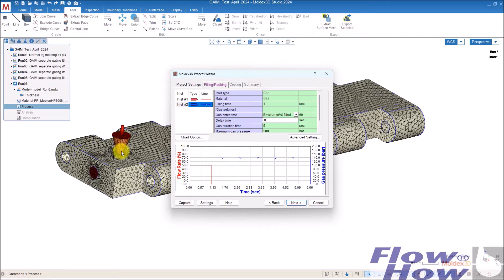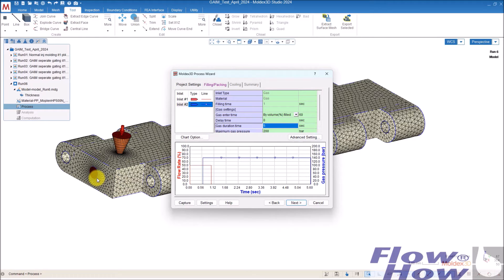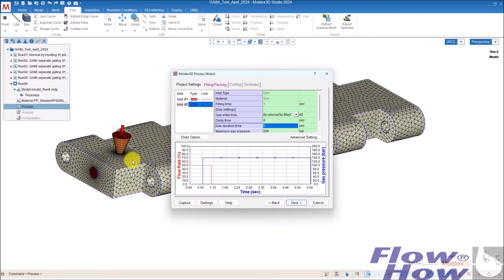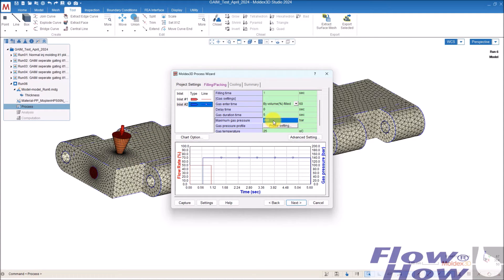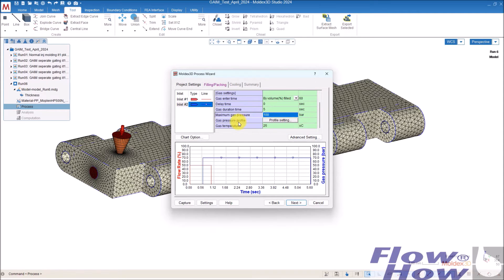So exactly when you close the valve gate here, it starts injecting the gas. And the gas duration is the time where you have the pressure or the gate open here and the pressure inside the cavity. And then you have the gas pressure. In this case, 200 bar, you can put it to, I think, a normal pressure around gas is dependent on which part, of course, you're making. But around 80 to 120 bar is not unreasonable. But let's just put in 100 bar and then, yeah. Nothing more to do here.